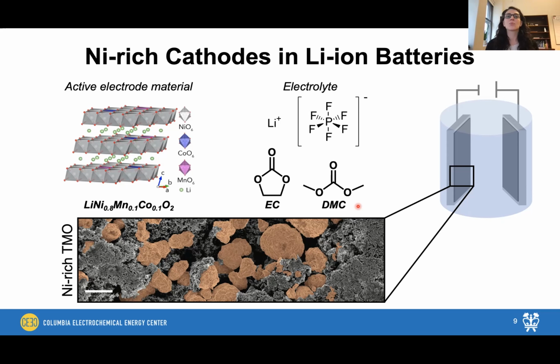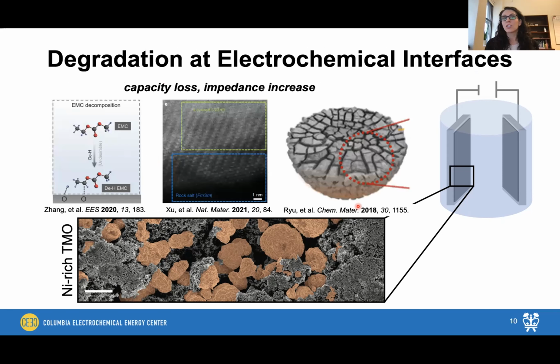Unfortunately, the issue is that whenever we start to remove cobalt from the active particles in these systems, the NMC811 starts to suffer from capacity loss and impedance increase whenever we start cycling the battery. And this is due to a variety of interfacial degradation modes that occur in these systems. So the first one that I'm showing here on the left is due to electrolyte solvent degradation that occurs at the interface between these active particles and the electrolyte solution.